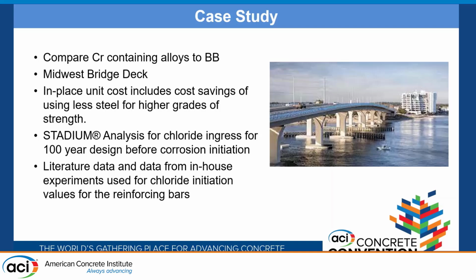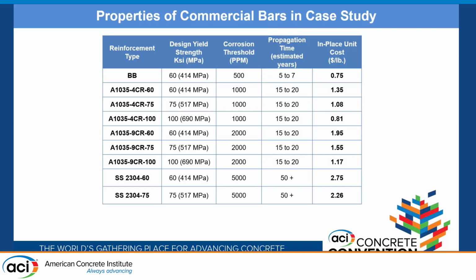We're looking at using Stadium analysis once again to analyze the chloride coming in for 100 years, based on the exposure conditions and literature data, as I mentioned before, from in-house experiments for chloride initiation values for the reinforcing bars. In some cases they might be a little bit conservative, but you can change those as is.